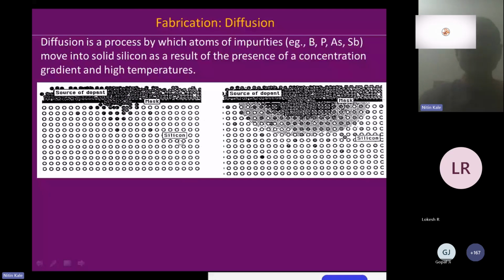Diffusion: you want to dope your silicon, right? You want to change the conductivity, create a source junction, create a drain junction, etc. How do you do doping? You will have some boron or phosphorus or antimony, something like that. That is the source of your dopant. You put that dopant in the furnace. You have your silicon wafers with openings in a mask, that is your insulator that I talked about, a silicon dioxide or a silicon nitride mask. It is through this mask that the dopants diffuse inside the silicon. That is diffusion, and the electrical conductivity changes because of that.